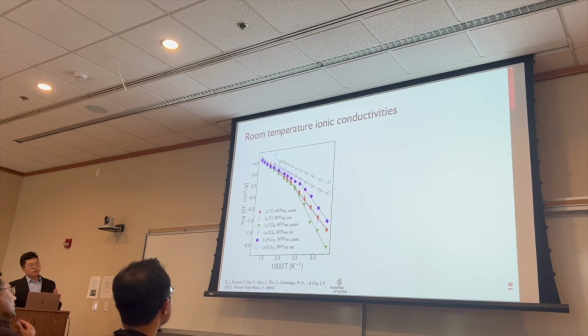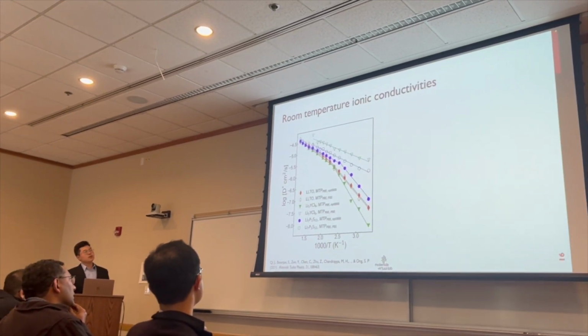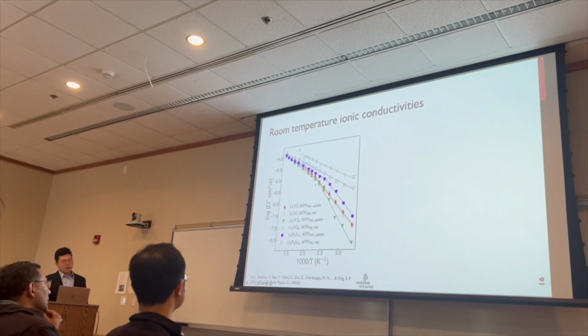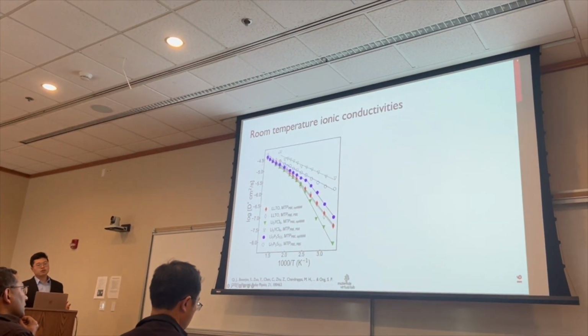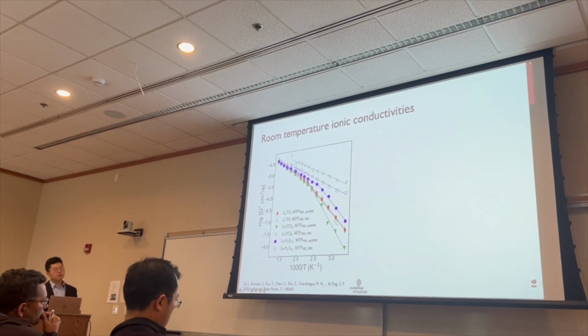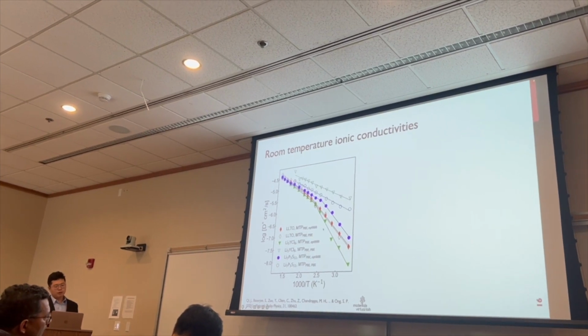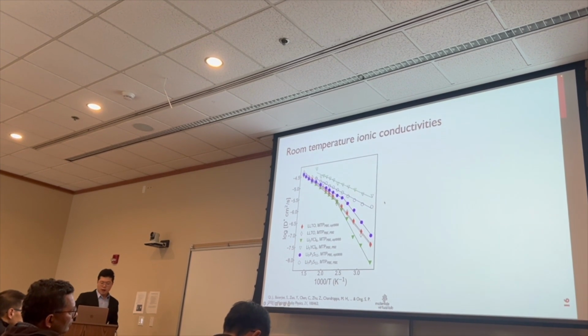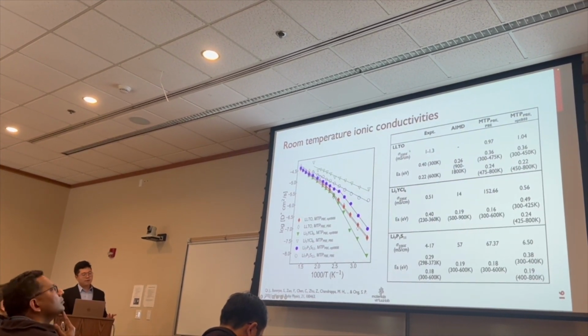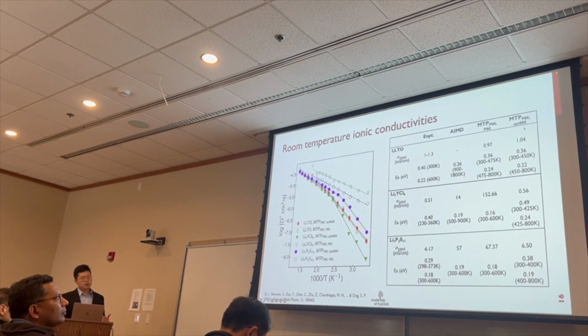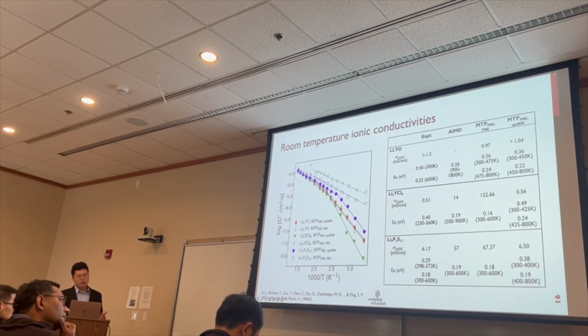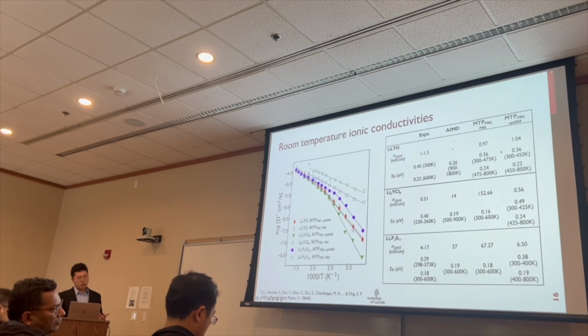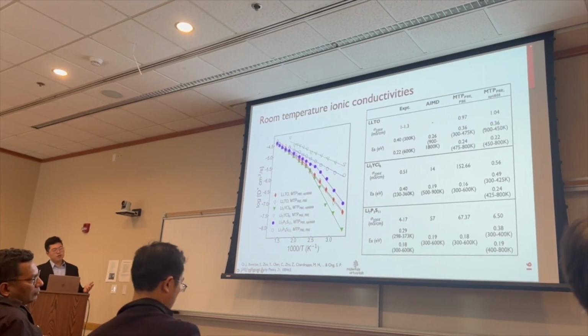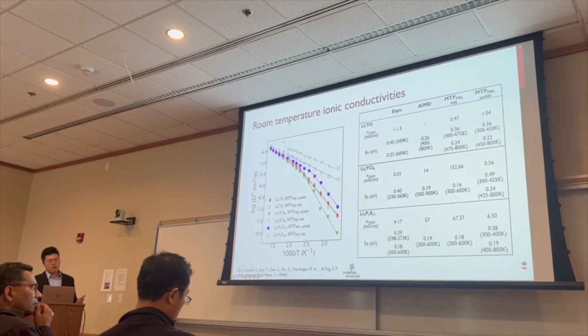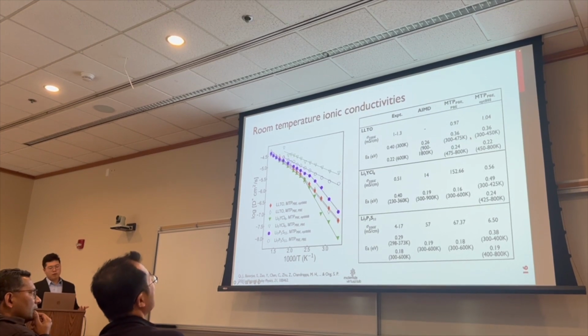Okay, let's go to the simulation of room temperature ionic conductivities. We use those different sets of moment tensor potentials to simulate room temperature ionic conductivity. You can see that in this simulation, we not only simulate the high temperature region above 500 Kelvin, we also study the room temperature region below 500 Kelvin, directly even at 300 Kelvin. We can look at the result in this table. Firstly, for LLTO, both moment tensor potentials get very good matching with the experimental result at room temperature, and they both capture the non-Arrhenius behavior, as you can see from the transition in activation energy at around 500 Kelvin.